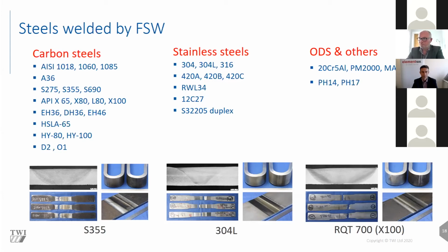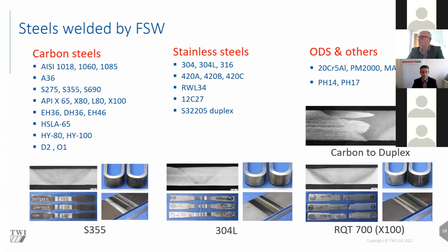We can also weld dissimilar grades. So one of our party pieces, if Nick moves on, is to actually weld carbon to duplex stainless steel, and that macro section through a weld shows the stainless steel being swept into the carbon steel and producing a very good solid bond. If you were to subject that to tensile testing, the failure would occur in the weaker of the two steels, which is normally the carbon steel. The weld itself doesn't fail. We find the weakest part of the carbon steel. Next slide, please, Nick.